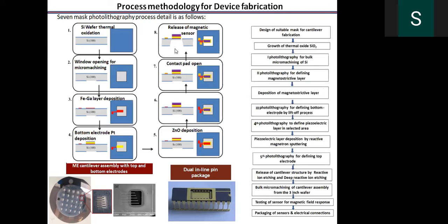After making that, you use the bulk etching technique, that is wet etching, to remove the bulk of the material, and finally releasing the cantilever from the main structure by using a deep reactive ion etching. So this is how the cantilever assembly, the device, looks in an actual device. This is a scanning electron microscopy image.